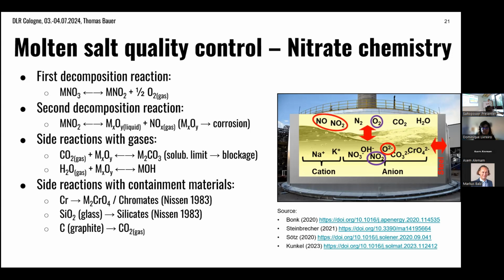Glass will also react. We know this from filler materials. Often they contain some silicates or silicon oxide phases, and they typically react with the salt. And also in the beginning, people used graphite seals. That's also not a good idea because graphite will react at 350, 400 degrees to form CO2, and then your seal is basically gone.